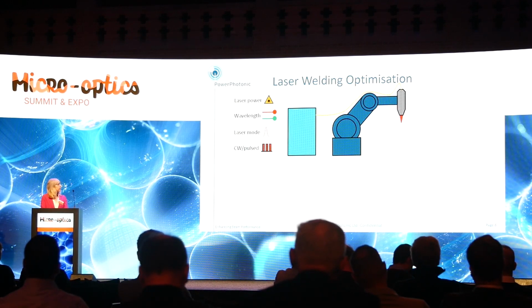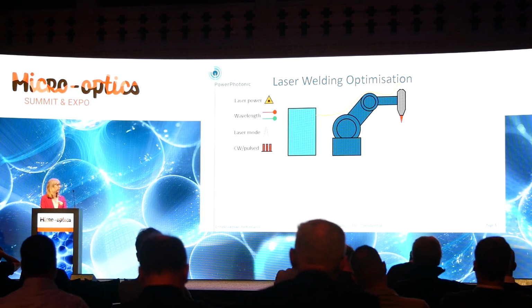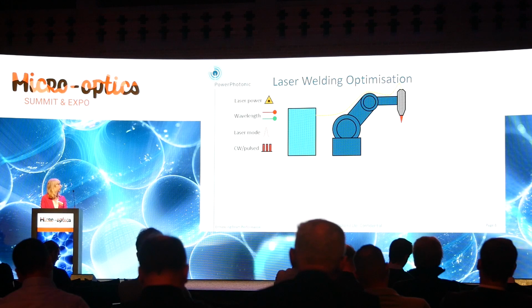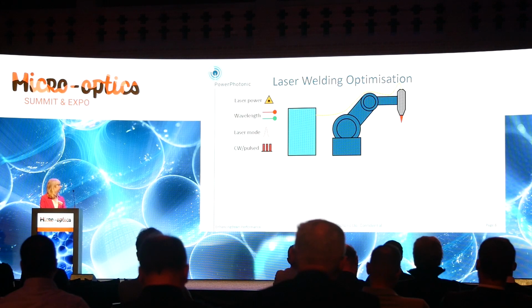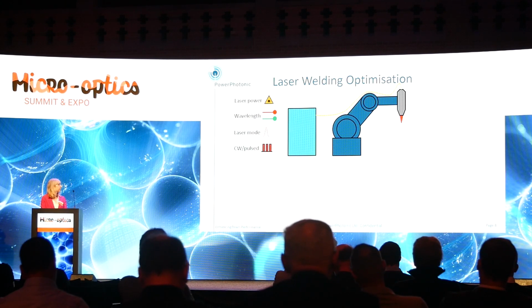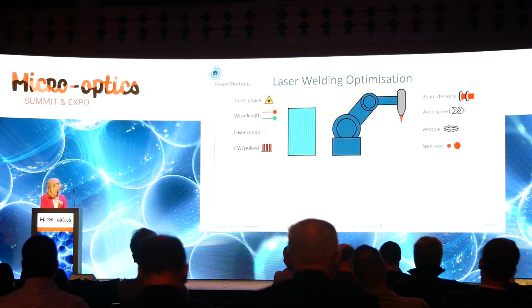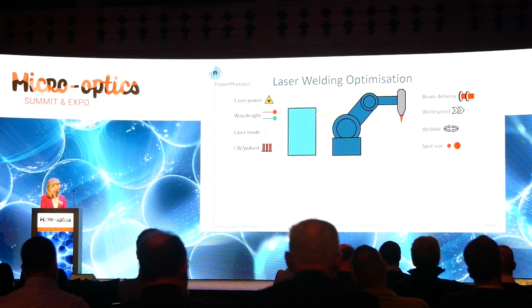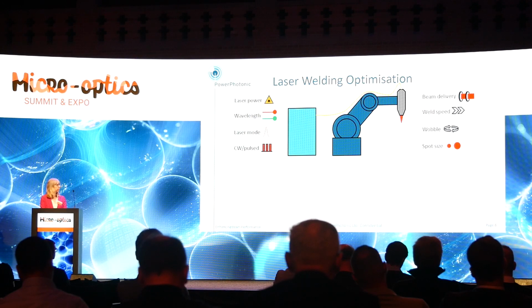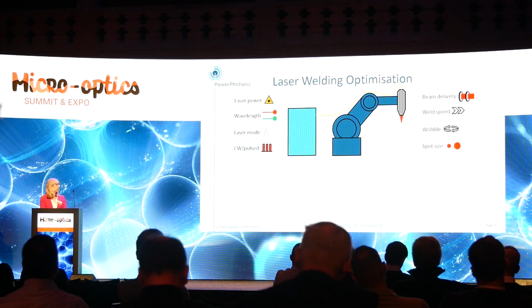Laser welding can be optimized in several different ways. You can change your laser power, so high power, low power. You can change your wavelength, so there is near infrared welding, and you also have green welding, blue welding. You can change your mode of laser, so you can have a multi-mode laser or a single mode laser, or a pulse laser or a continuous laser. Other ways are you can change your beam delivery, which could be your spot size, your focal length, all of your optical system. You can change the speed of your weld. One of the most common things in welding is to add wobble.